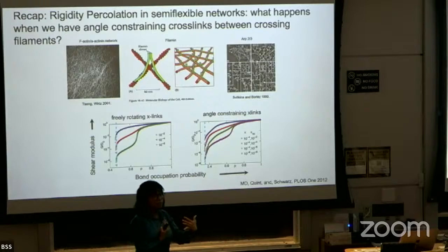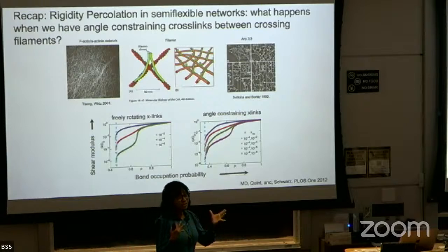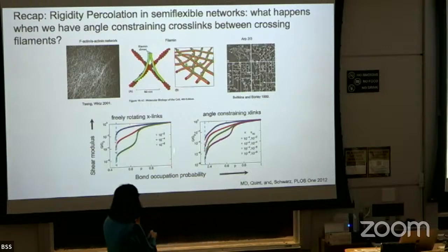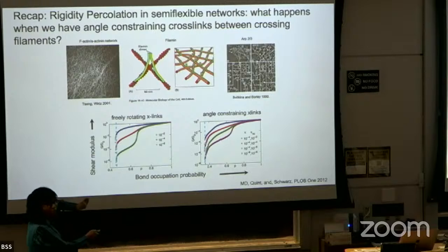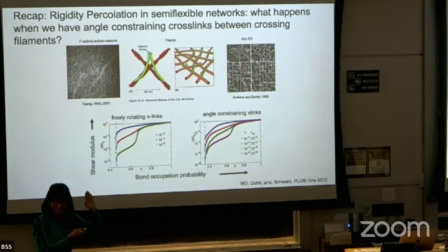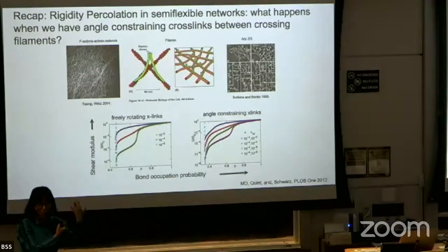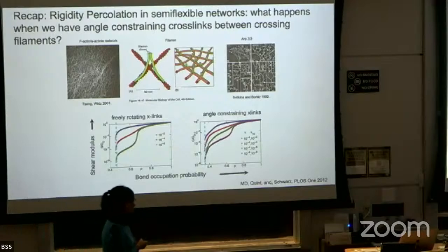So basically, if you add more and more constraints, then you can have rigidity with less and less material. So you can ask, how much further can this move, right? Can we keep going down all the way to 0 as you add more? That's not true. You stop at connectivity percolation. So connectivity percolation threshold is usually less than rigidity percolation threshold. That's where you stop when you have all possible constraints that you have wanted to add and you've added them.